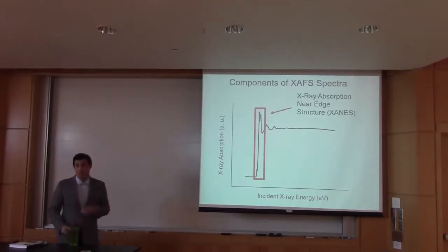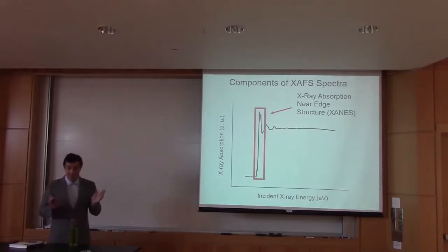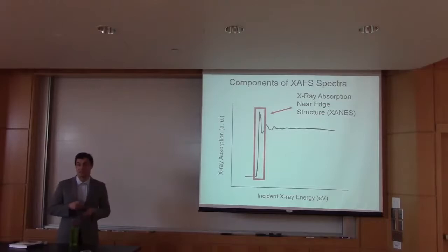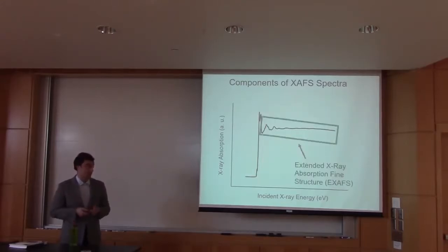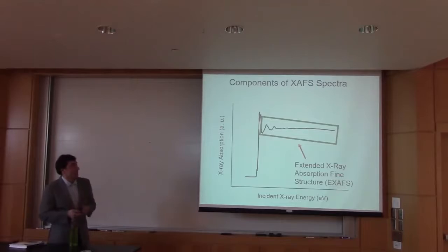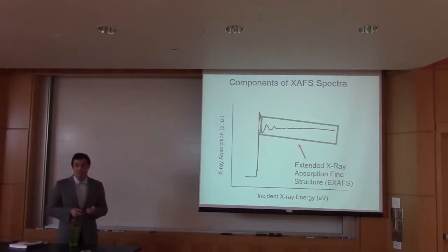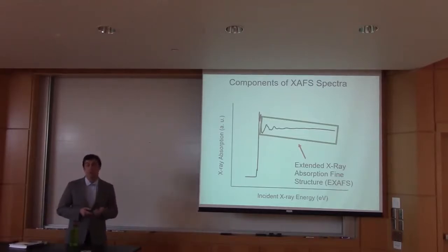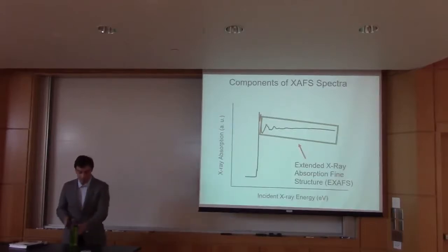So this early region is called XANES, or X-ray absorption near-edge structure. This can tell you things like oxidation state of the metal you're looking at and some other really important things. But we were less concerned with this because we knew those values for our sample, and we're more concerned with the extended X-ray absorption fine structure, which is also called EXAFS and also confusing. But these XAFS and these outer oscillations can tell you, most importantly, the distance between the absorbing atoms and its neighbors, which is incredibly powerful.